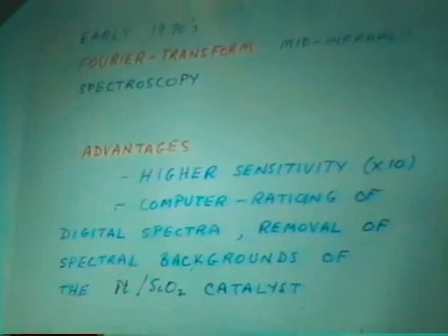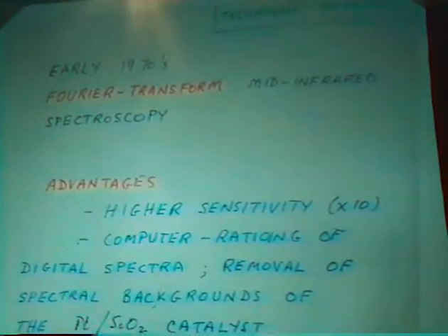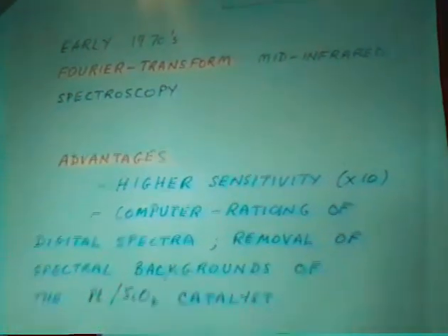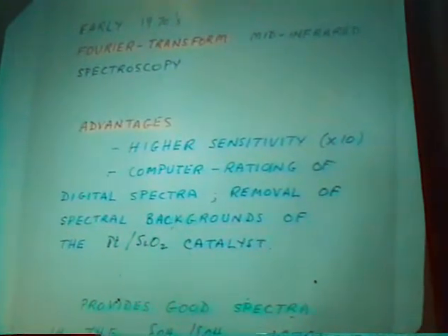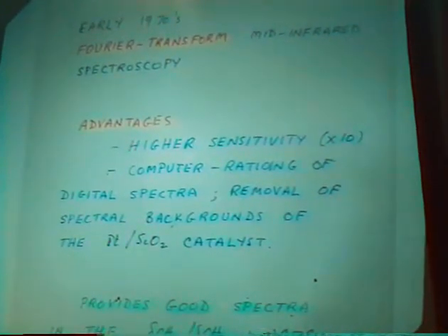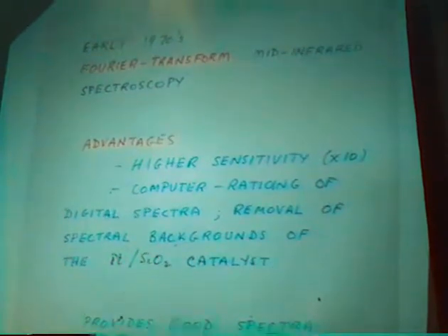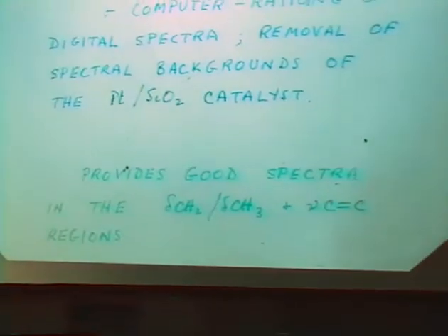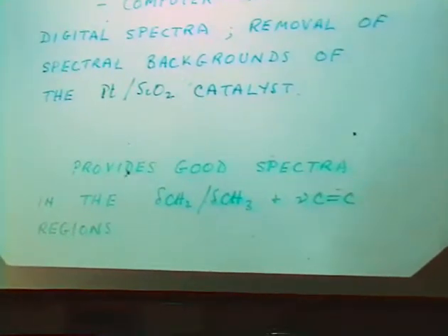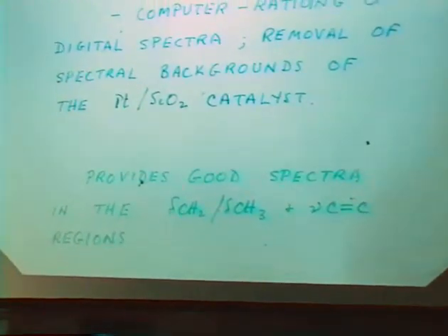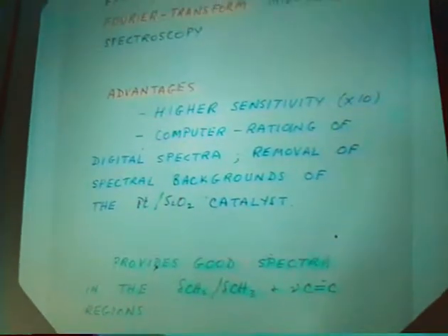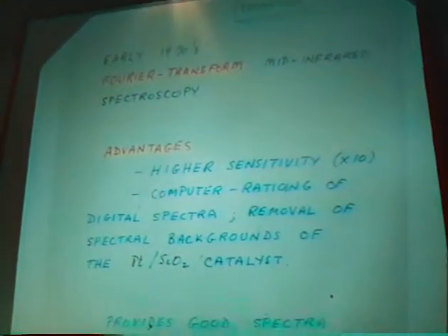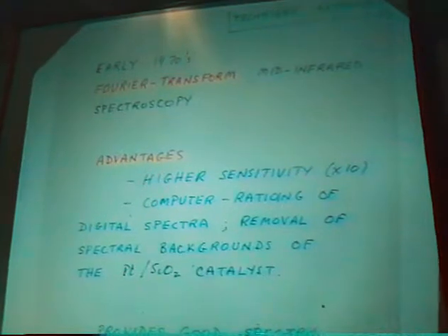Well then, about the early 70s, FTIR came along, and the principal difference here was it gave us much more sensitivity, where previously we struggled to get species from hydrocarbons, now it was relatively easy. In order to go from the interferogram to the normal spectrum, you had to have a minicomputer or a microprocessor, and that gave you computer ratioing, and then at last we caught up with Bob in being able to subtract out the oxide background, even in the angle bending region, and to get good spectra down there.